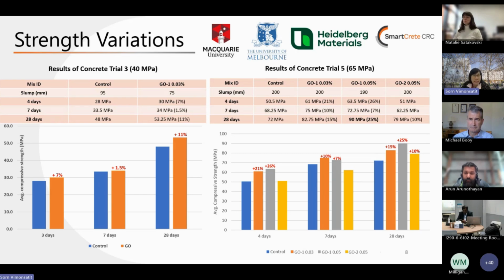Okay, so first I'd like to present this. The control is the blue one, the one without the graphene. And then we have the slump, as Michael already said, that we were happy with, coming up with the sequencing mixing method that Michael mentioned, that managed to retain the slump and achieve what we were not able to achieve before. And then we tested at 4 days, 7 days, and 28 days.